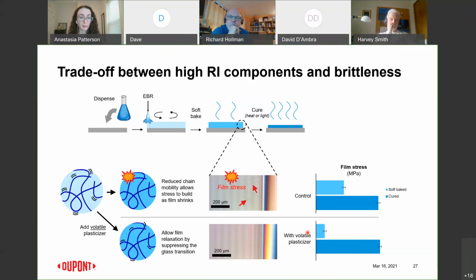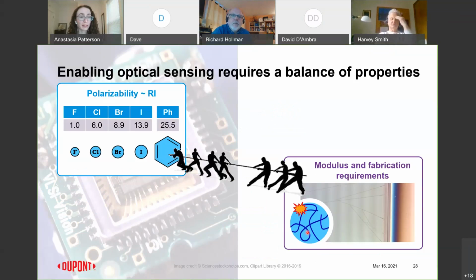So that was three challenges that we met with high refractive index materials. We designed in, on the chemical side, high polarizability functional groups. And those brought up a number of challenges in terms of the film properties and the solubility. And so working with our customer, we were able to fix those by really diving into the process.